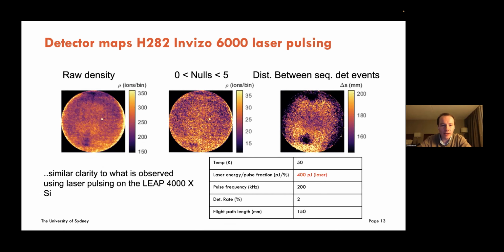For the laser pulsing, I don't see so much crystallographic information, at least for the experimental conditions that I've been looking at, but it might again be a case of just optimizing those, cycling between 100 and 800 picojoule laser energies. This was just an example from 400, but there is still some crystallographic information that we're collecting there, which we could use to study potentially site occupancy information, the gamma prime, and also help with calibration.